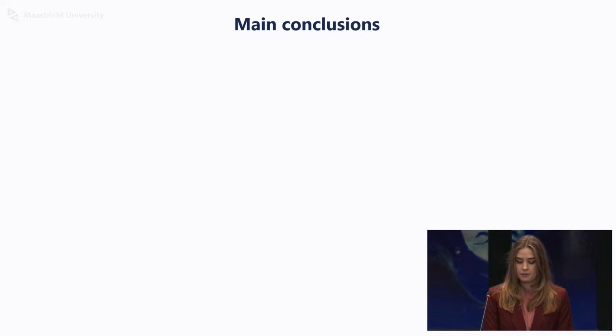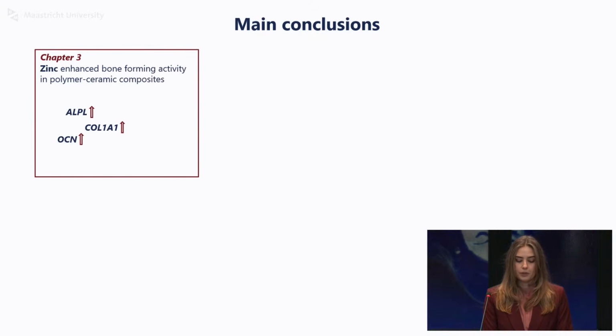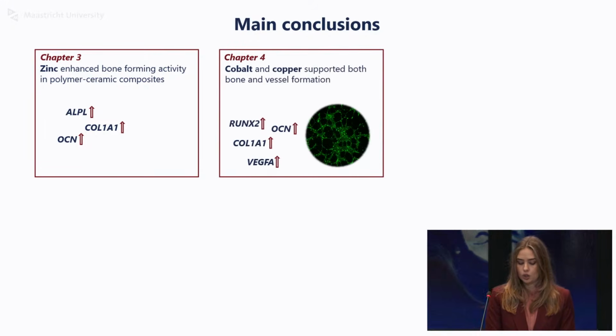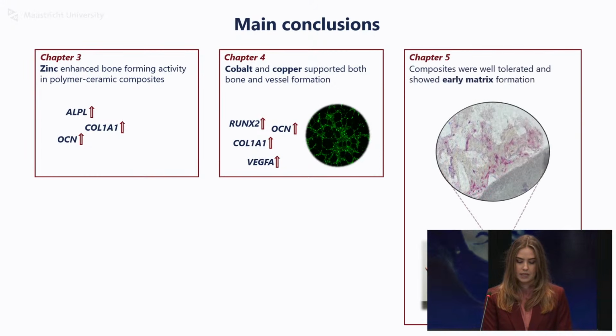To summarize the main findings, in Chapter 3, zinc added to polymer ceramic composites enhanced bone-forming activity. By further adding cobalt and copper to the composites, we achieved materials supportive of both bone and vessel formation. In the animal model, these materials were well tolerated. They integrated with the surrounding tissue very well, and we observed early signs of new tissue formation.